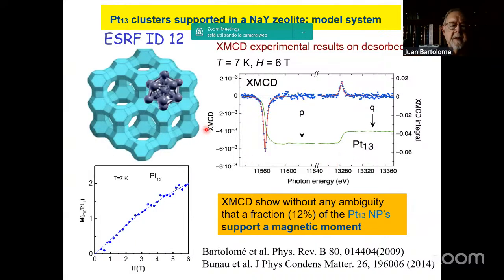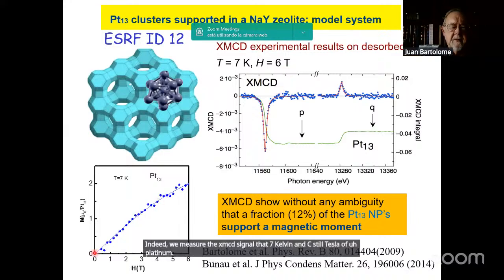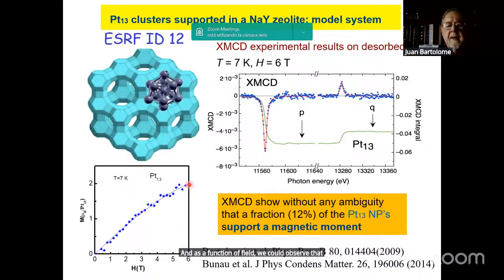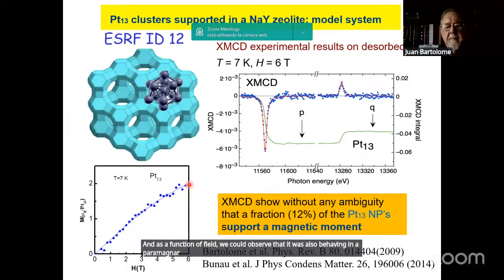We still did some more experiments on clusters. Platinum clusters can form well-packed clusters that can be embedded into zeolites. In this case, I'm showing sodium Y zeolite. These clusters are strongly packed, and we were wondering whether they would also support magnetism. Indeed, we measured the XMCD signal of platinum at 7 Kelvin and 6 Tesla, and as a function of field, we could observe that it was also behaving in a paramagnetic way.